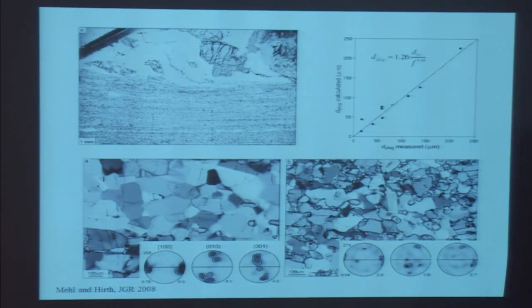This was worked on a lot in the material science community because of wanting to create really fine-grained, strong ceramics. If you wanted to put them into weird shapes while you were processing them and you didn't have a way of keeping the grain size fine, then when you were done with it, the thing would crack and break. So a lot of work was done to say, well, if you mix a second phase in there, that keeps the grain size fine, and then we can do all kinds of amazing stuff. It's something that the samurai figured out a long time ago in making their swords, just by luck. They didn't know what they were doing. But when they made those amazing swords with the super sharp blades, what they were doing was using a little bit of carbon on the grain boundaries that was pinning the steel. So they could form it at high temperatures, and when it cooled, it would hold a blade really strong.